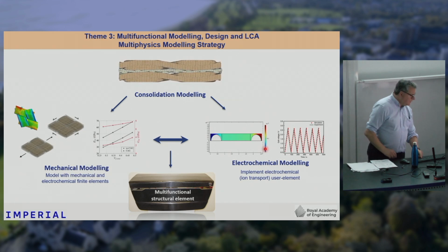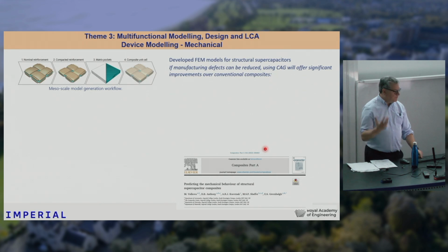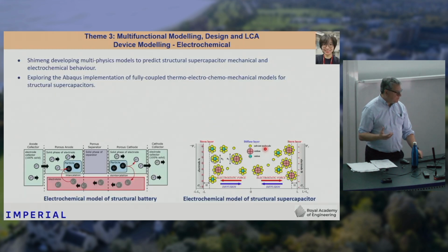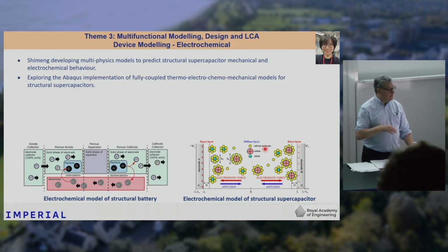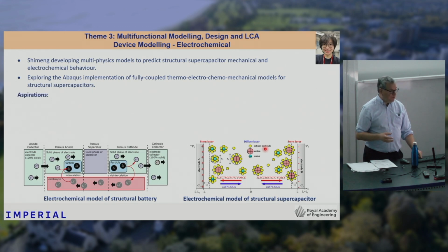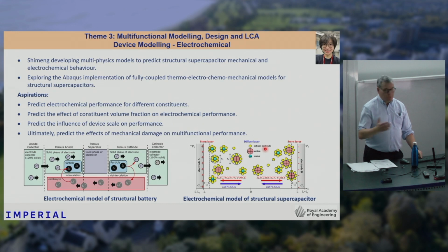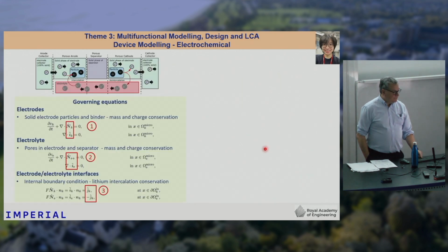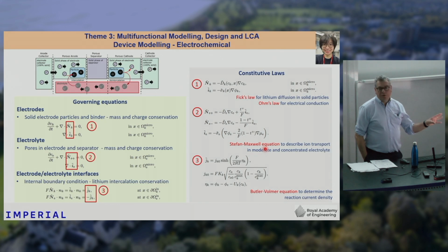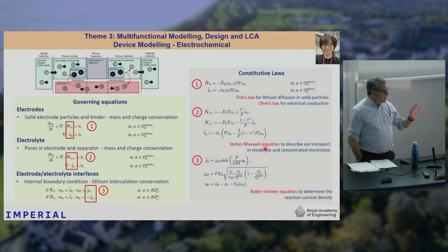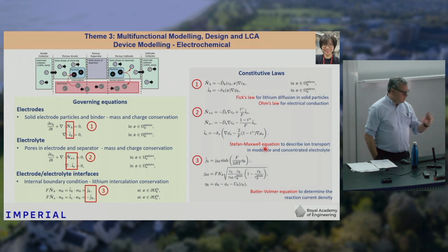Where we've taken that is we've done some elastic modeling as shown here. I'll skip over this quite quickly. And also the electrochemical modeling we're working on. Abaqus has just introduced a battery model into the code, and we're now starting to explore using that for electrochemical modeling. And as I said, one of the aspirations there is to allow for damage and things to be introduced. These are some of the governing equations, but I wasn't going to dwell on these. But what we're trying to do is take that battery model and see if we can apply it to a supercapacitor model. And do that by manipulating some of these constitutive laws to allow us to do that.